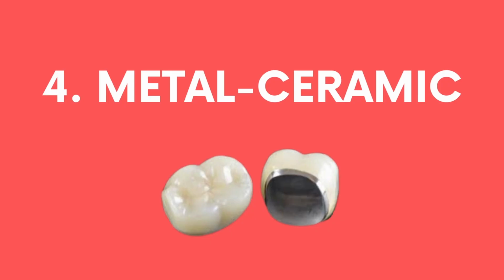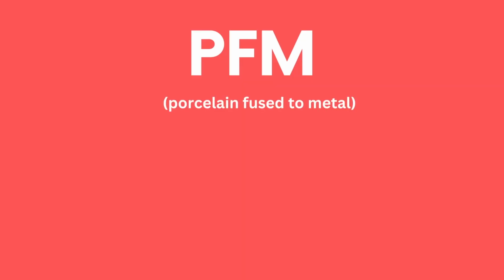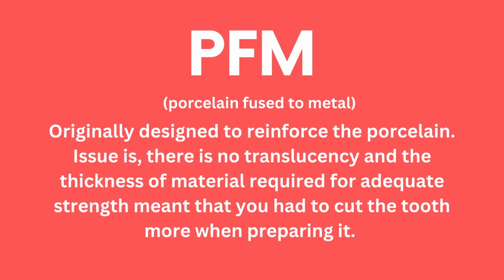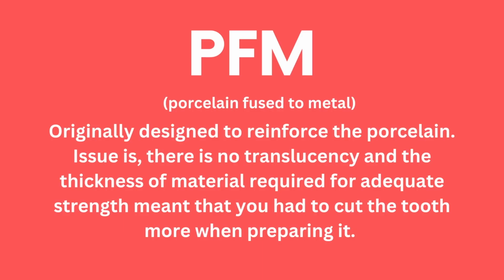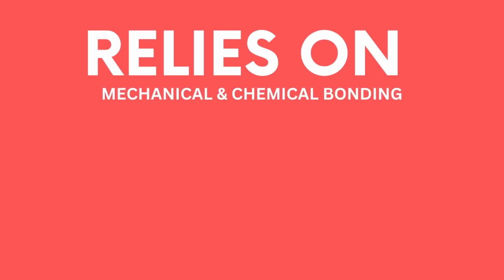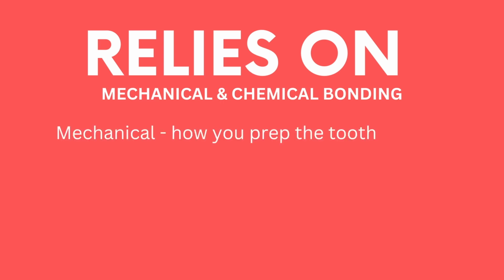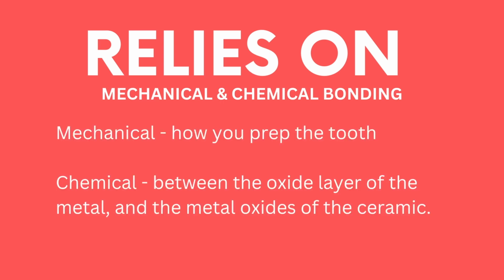Metal ceramics. Probably the most common and the one that we always were told to do at university is the humble PFM, also known as porcelain fused to metal. The metal originally was designed to reinforce the porcelain. The issue is there's no translucency. To think back at uni, I thought they were aesthetic. The thickness of material you require for adequate strength means you have to do a significant amount of prepping. It relies on a mixture of mechanical retention and chemical bonding. The mechanical comes from how you prep the tooth. The chemical comes from the oxide layer of the metal and the metal oxides of the ceramic.